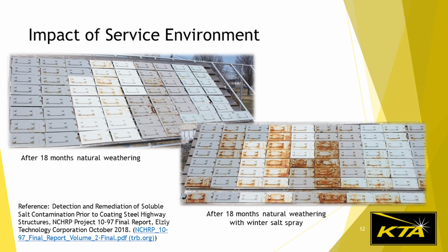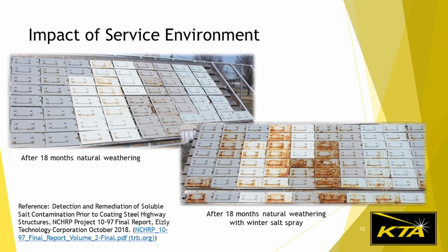The slide shows here the negative effect that a harsh environment can have on painted steel structure. The 4 different colors indicate 4 different coating systems. So the panels had varying degrees of surface prep before coating application. The photo on the left is after 18 months of just natural weathering, and the photo on the right is 18 months with winter salt spray.